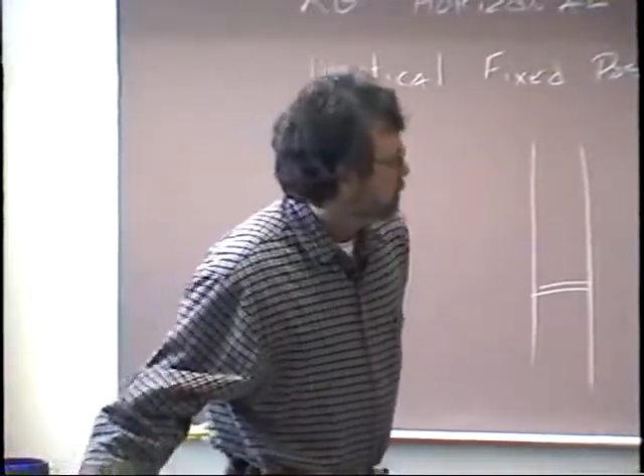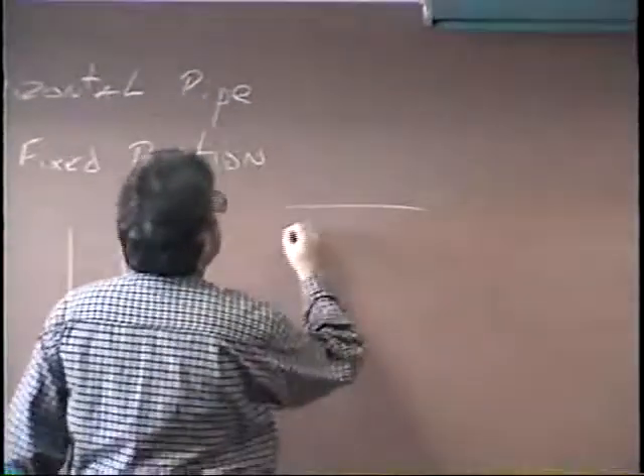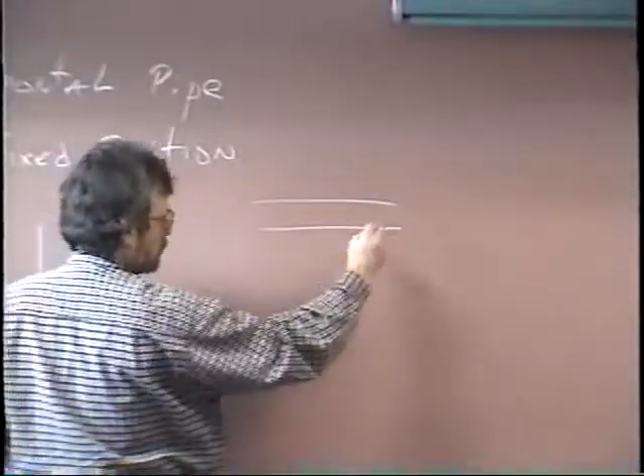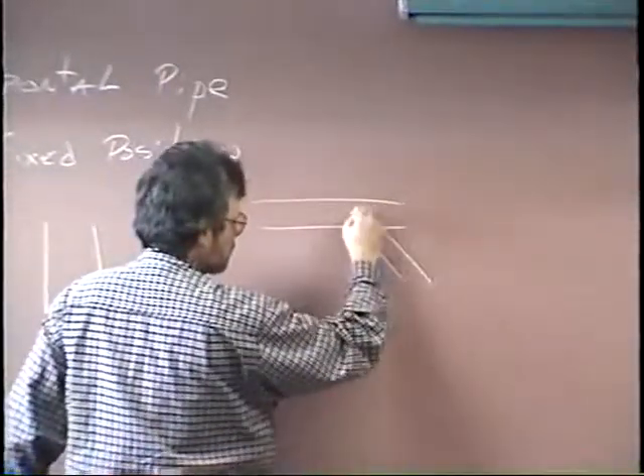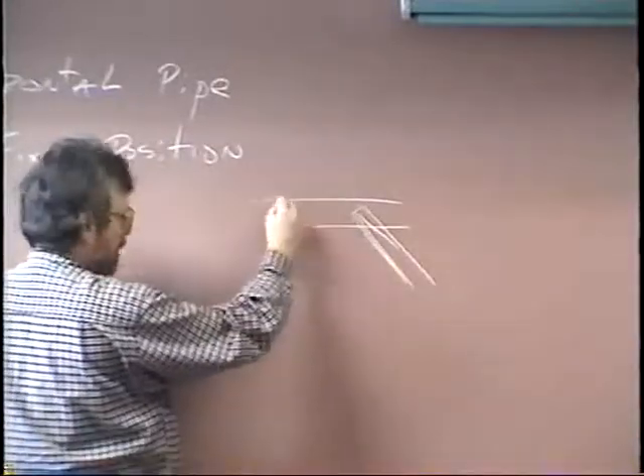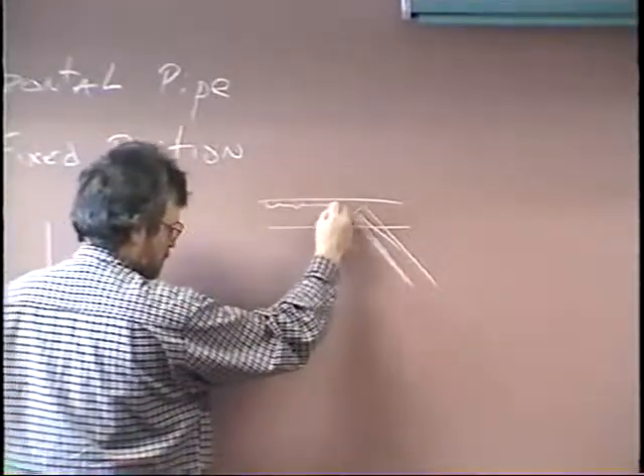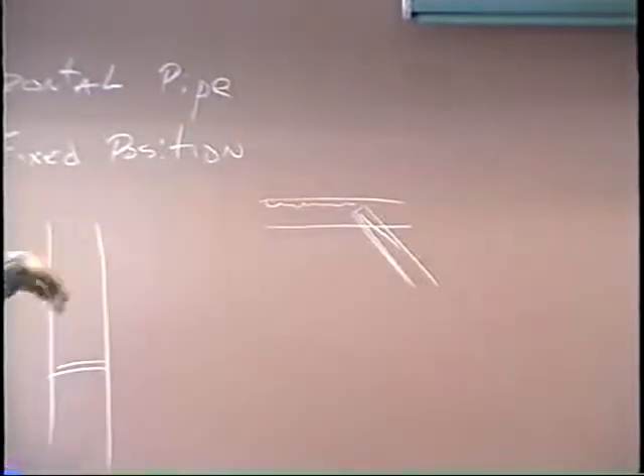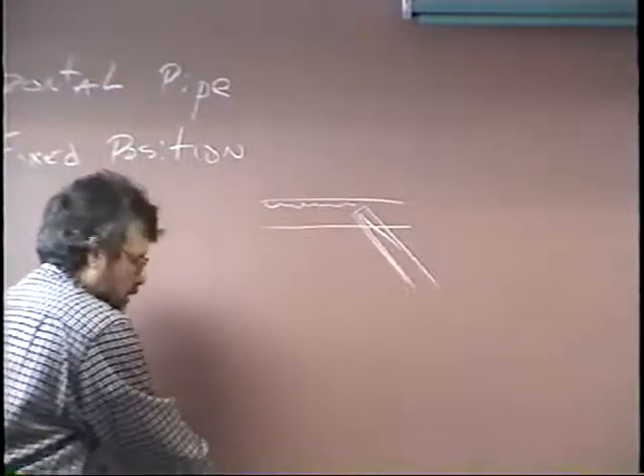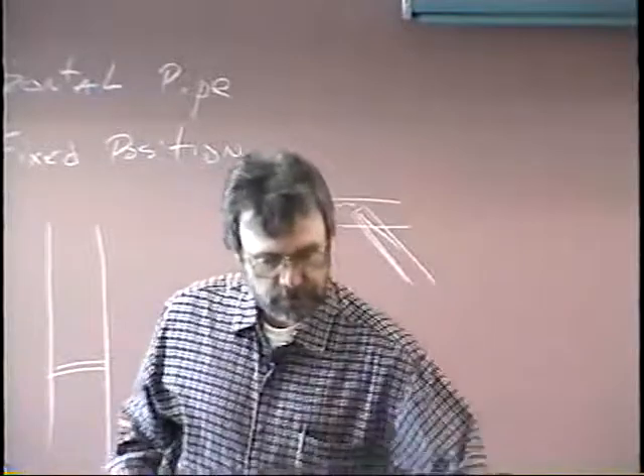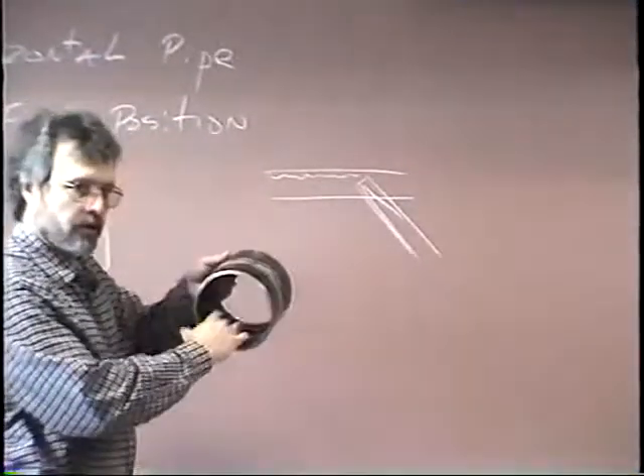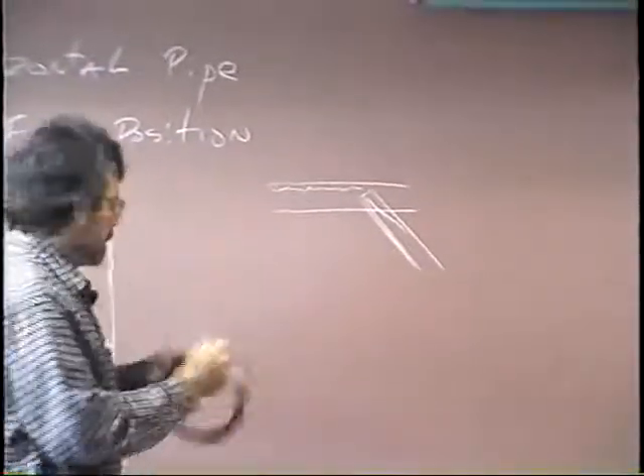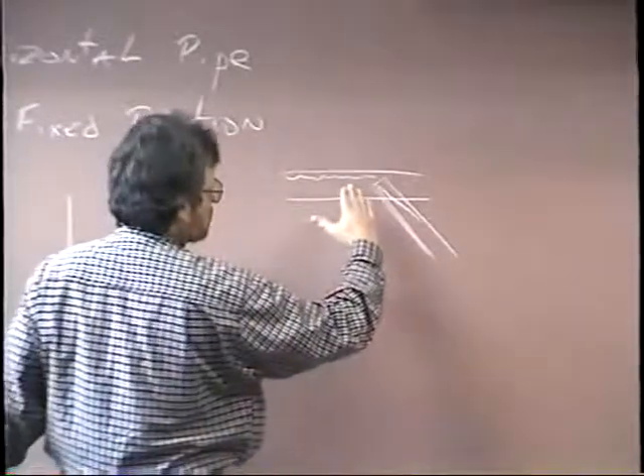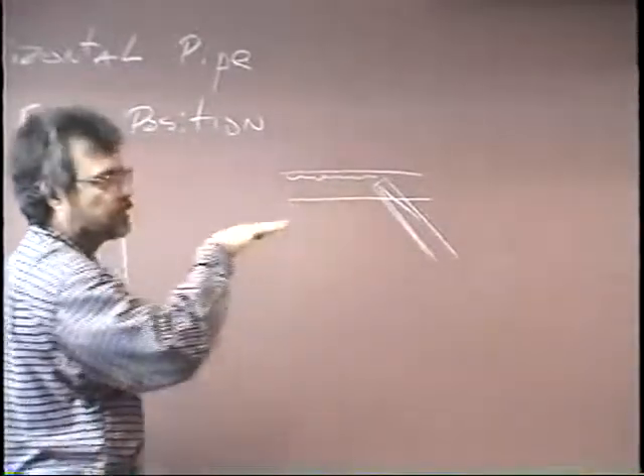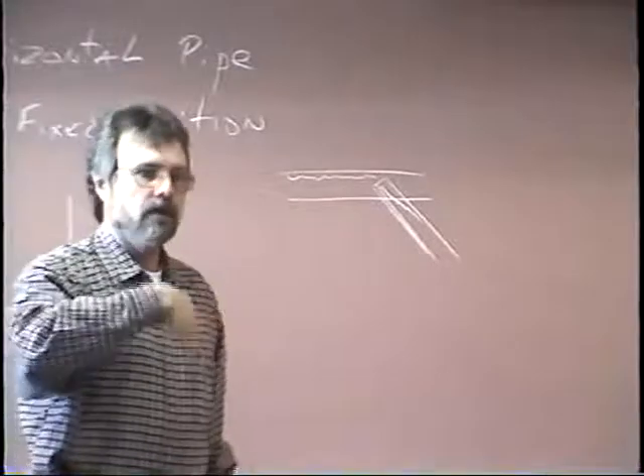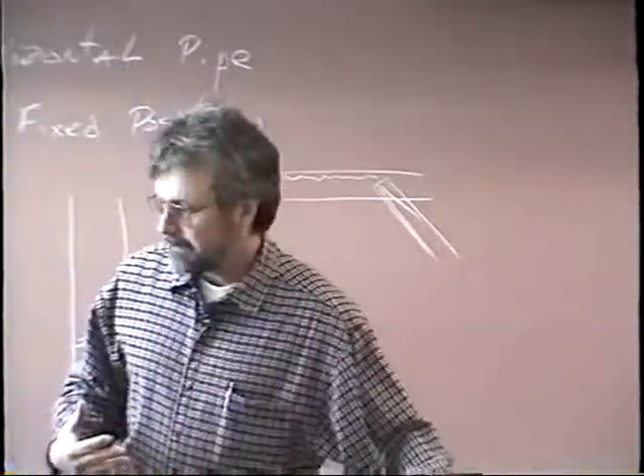When you're welding that root bead, if you don't use a slight up angle on your electrode, gravity is going to pull down on the inside of the pipe. And those of you that have done some of this know what I'm talking about. You'll get internal undercut on the upper side of the bead. So you want to have a slight up angle on this electrode as you're coming through, so that the force of the arc coming off the end of the welding electrode helps to counteract that tendency.